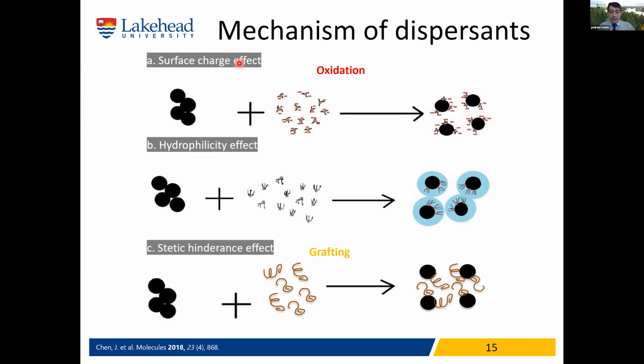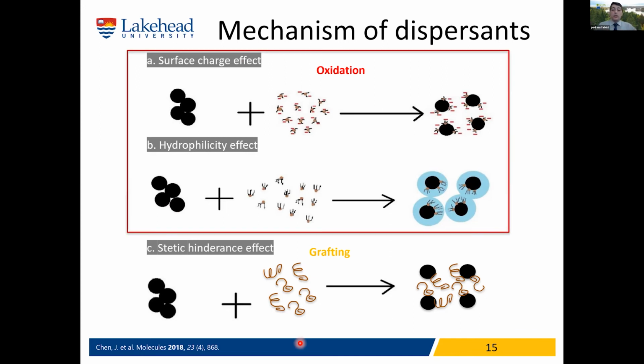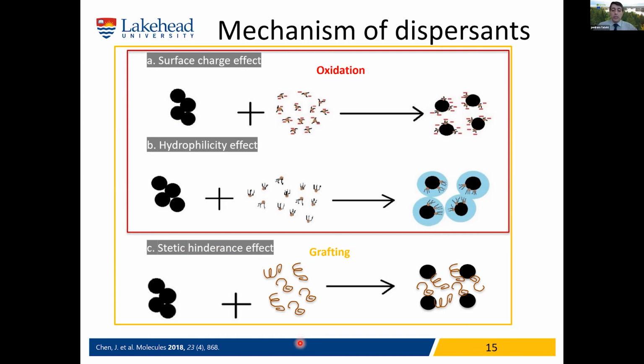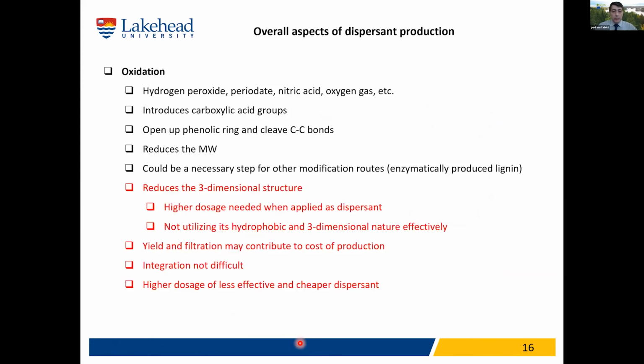So that's the second approach. The third one is steric hindrance. That means that you adsorb something on the particle so that the big particle cannot agglomerate. When you do oxidation, the first two are targeted basically, but when you do grafting, all three are affected, and that's very important. So again, I have 3 more slides to finalize this.